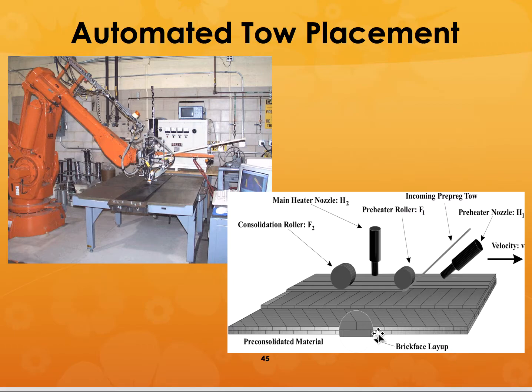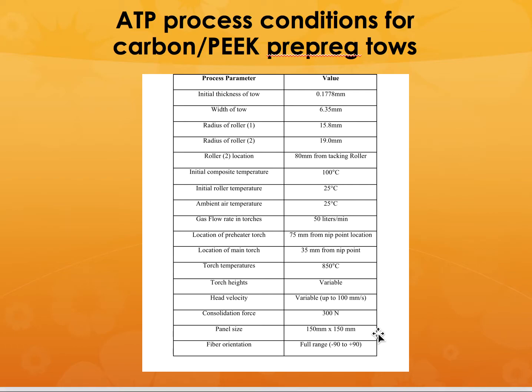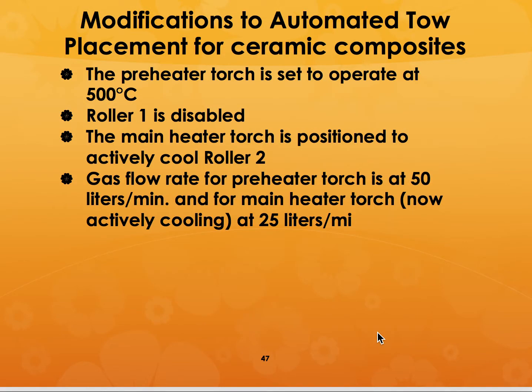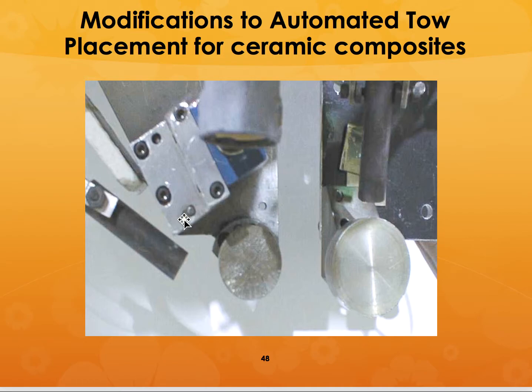So you have two rollers, and these are some of the processing conditions for carbon prepreg toes, and we modified that for ceramic composite toes. So in that case, we had to make some modifications. So the original preheater torch is set to operate at 500 degrees centigrade. So we disabled one of those rollers because we didn't want this thermoplastic binder to be melting and flowing all over the place. And we also reduced the gas flow rate of the preheat torch to reduce the heating conditions. So this is the close-up view of the rollers, two rollers. One of the rollers is a preheating roller, the other one is the tamping down roller.